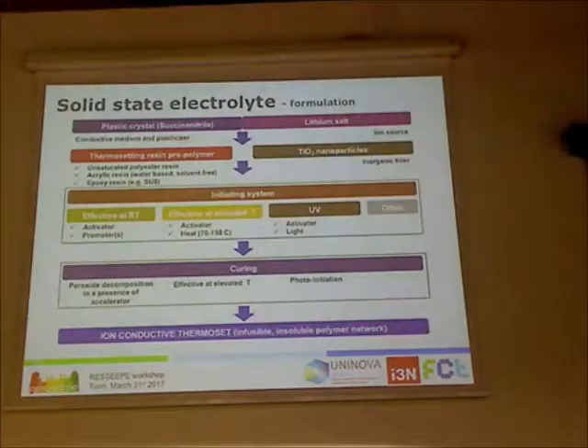To create these on foils, it's important to have a solid electrolyte in between. Of course, you lose in terms of ionic conductivity compared with liquids or gels, but in terms of safety it's much better. So we have developed electrolytes based on thermosetting resins, where we mix some lithium ion salt,